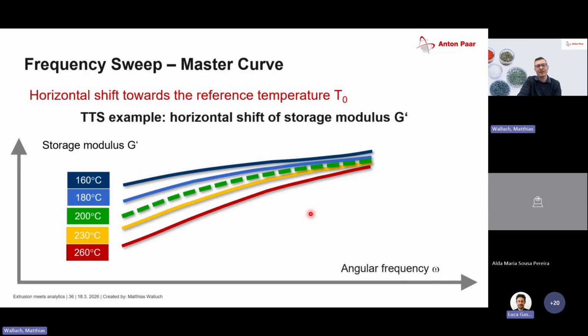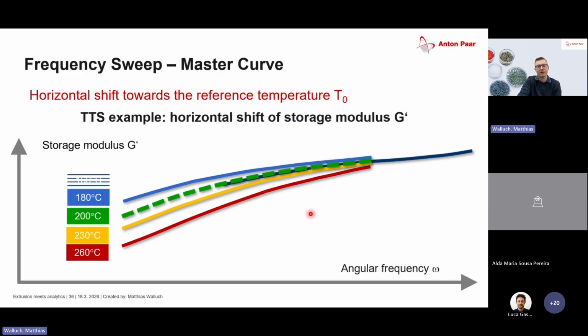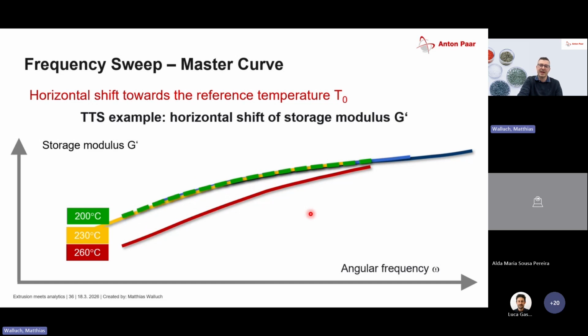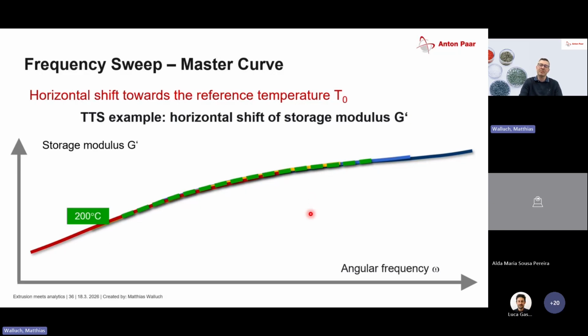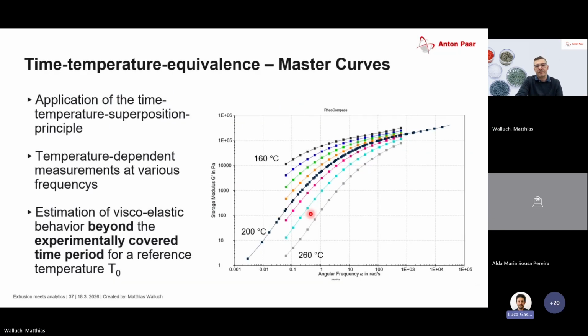And when you see here what the TTS principle does, it's just shifting curves to a reference curve. So we start with a high temperature, we shift it to the right, and the lower ones will shift to the left. So as you can see, the x-axis is the angular frequency, and so therefore the data fits together. So there's this correlation between the temperature-related behavior and the time-related behavior of polymers. And now the question is, does this also work for materials in reality, not only in a simulation?